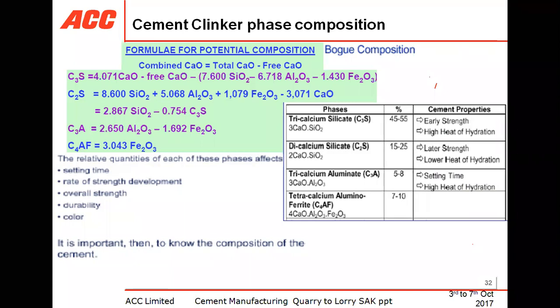But when you analyze in equipment like XRD, X-ray diffraction, or microscopic analysis, also carried out in cement plants, we will get the exact, practical percentage of tricalcium silicate, practical percentage of C2S and C3A. So you will get a perfect picture of your actual clinker quality if you analyze this sample in X-ray diffraction and microscopy. You can calculate the same C3S and C2S through this Bogue composition, but you will get a theoretical value, while the actual value you will get from XRD and microscopy.